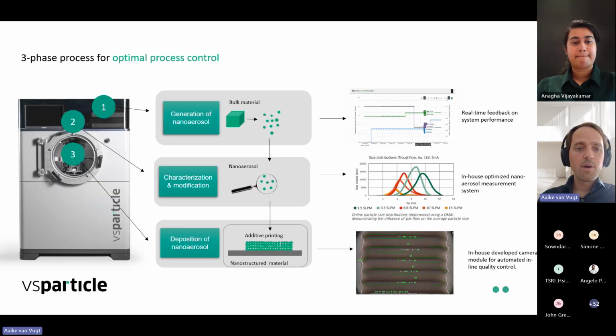The nice thing about this 3-phase process is that the first phase is converting the bulk with these high temperature plasmas into nanoparticles. Then we can measure if it's needed. We could measure the particles in line, and then in the last step, we print them. There are already all kinds of capabilities we can add to do inline quality control so that you really know exactly what the material is that you are printing.